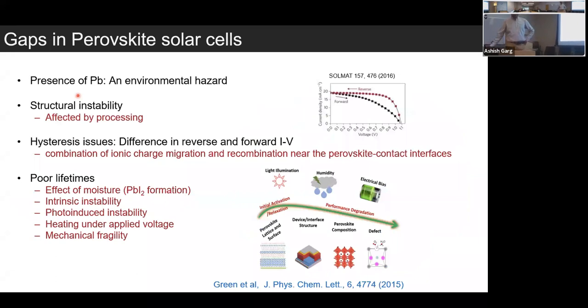So there are several gaps in perovskite solar cells, despite all the progress that has been made. One is, of course, the presence of lead, which is an environmental hazard. And second is structural instability. Perovskites have a problem of being structurally unstable whenever you apply heat, or even light stress or moisture-related stress. Any kind of environmental stress makes the structure unstable, and perovskite tends to break into different compounds. This is a very critical problem in perovskites.